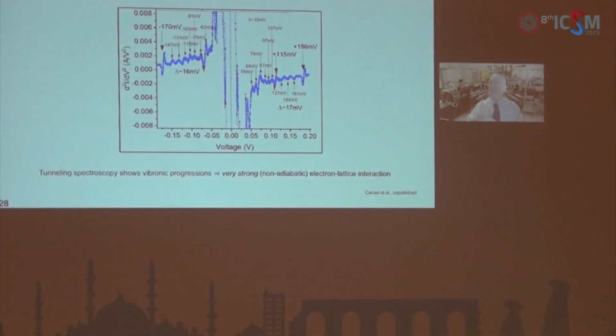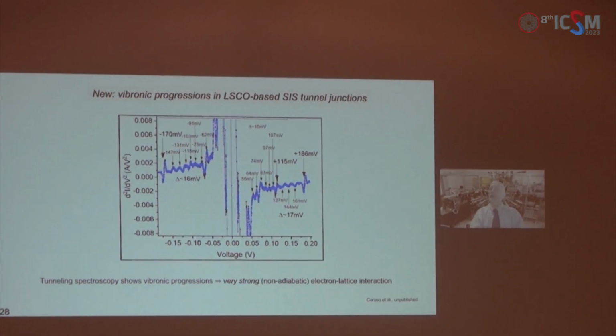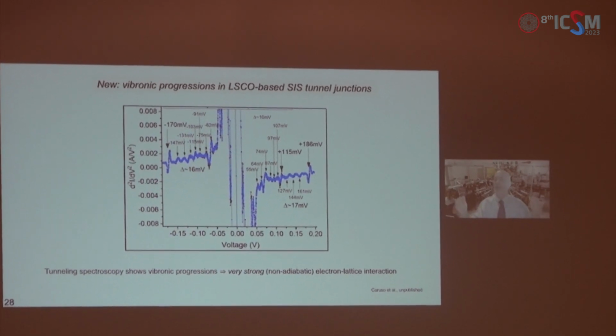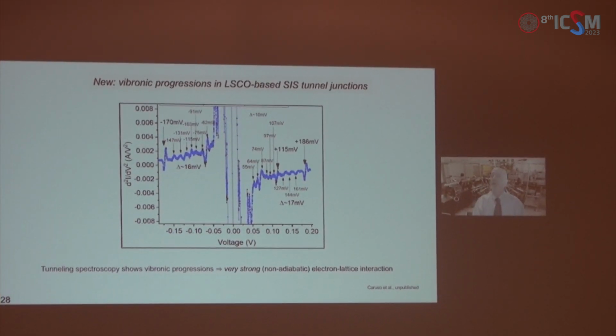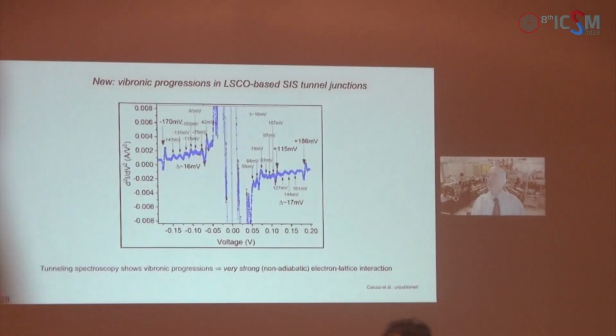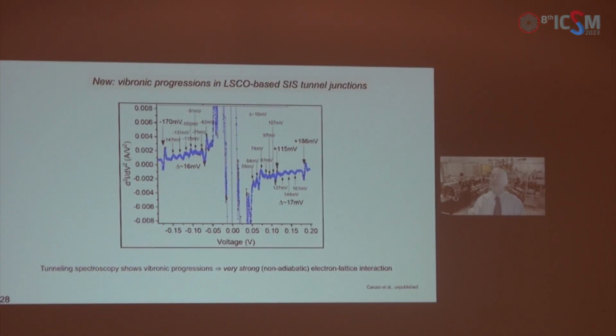Actually, the short answer is no. There are a number of theoretical models. I would say the mainstream thinking about cuprates will just consider a single copper oxygen plane modeled by a single band, 2D Hubbard model or t-J model. In some cases, people will do 3 bands to include hopping between copper and oxygen, which obviously is there. But in all of these cases, it's just a simple copper oxygen plane. And then they tune the doping level by changing the chemical potential.